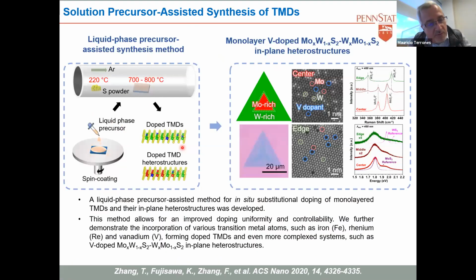And this is just a method that we published last year, but it's sort of a universal method. So in this case, in principle, you could dope with any element your monolayers of tungsten sulfide, moly sulfide, moly selenide and tungsten selenide. The way to do it is that you use a liquid phase precursor, right? So usually it could be an organometallic compound, and that would be your dopant here. And in this liquid phase precursor, you will also have the moly or tungsten atoms here. So you spin coat, you put here your substrate, you put your sulfur chalcogen powder, could be selenium or tellurium powder. And then what you end up having is you can have doped